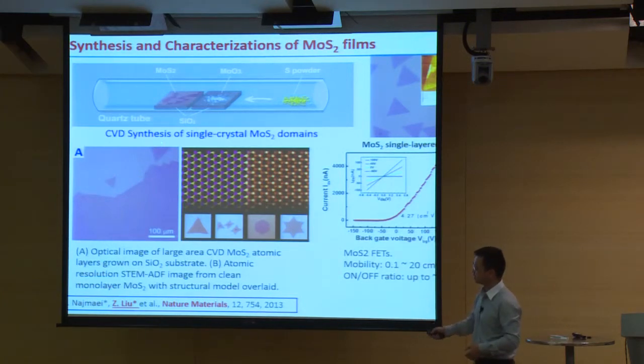And we can also get large area polycrystalline monolayers, from a couple of hundred nanometers to 100 microns. And also we examine this material under microscopy, so a lot of areas are defect-free. And we can get quite a lot of different shapes, like triangles, hexagons or stars. And we make some devices, and test the mobility and on/off ratio. The mobility is 0.1 to 20, and the on/off ratio is 10 to the power 8. So these values are comparable to the mechanically exfoliated molybdenum sulfide.